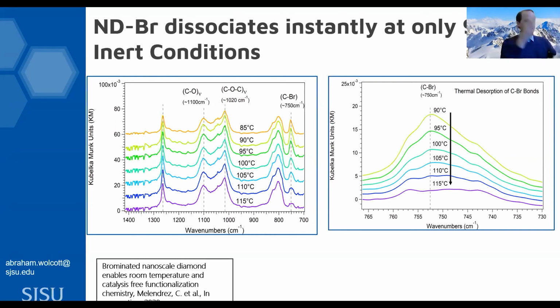And so we replace these small alcohol groups with the bromide ion, which is 80% larger in its atomic radii. Therefore, the more bromine that you place onto the surface, the more destabilized they're going to become. And so this can be viewed as either a deficit or an asset. And I haven't been able to plot up some recent data, but we've almost been able to completely purge all of the alcohol groups from the surface, and had almost 100% conversion of the alkyl-bromides on the surface. And it really comes down to not purifying the sample as much, ironically enough.